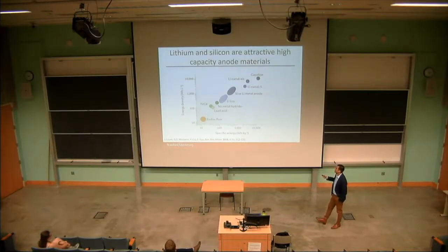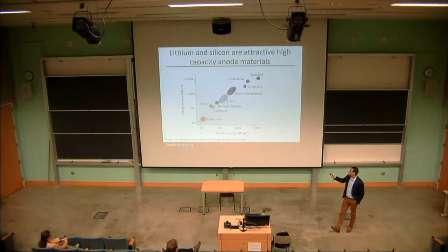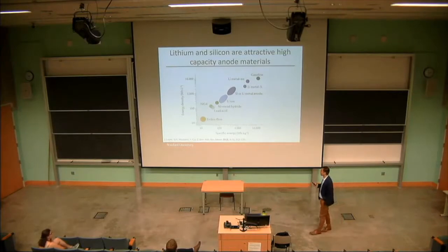Lithium ion is really, really popular. That's what's in all of our cell phones, all of our laptops nowadays. If you were to just take traditional lithium ion materials and then switch the anode to either silicon or lithium metal, that gets you up to here, which is already quite an improvement. And then when you switch the cathode side paired with lithium metal to metal air or a metal sulfur battery, we can actually start to even approach gasoline level energy densities. These are theoretical numbers, so obviously we have a long way to go before these technologies can reach this, but it shows, I think, the promise of these technologies and why they're worth studying.